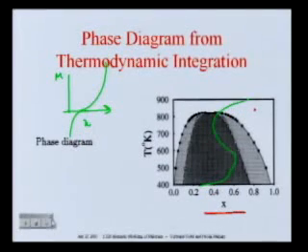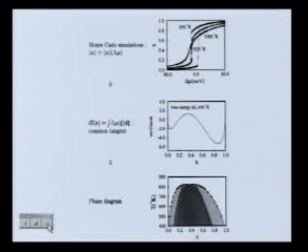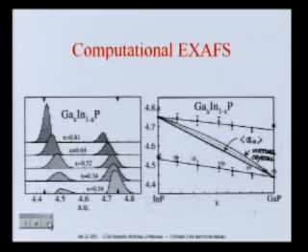And so you can calculate your phase diagram, and at the end for this system, it would really look like this. Below 820 Kelvin, you open a miscibility gap in which the two systems don't want to mix together. And so in many ways, semiconductor alloys are really model solutions. And below the critical temperature, they start to segregate. And of course, you can do a lot of other intriguing things. That is, in your simulation, you figure out, say, the distributions of gallium-phosphorus distances or indium-phosphorus distances at any given concentrations.